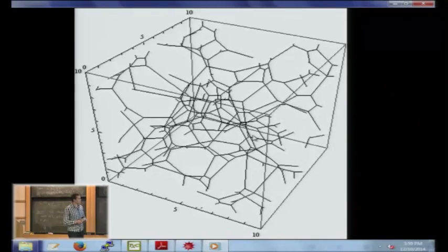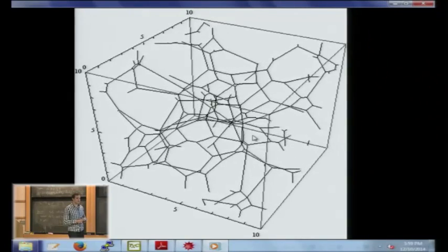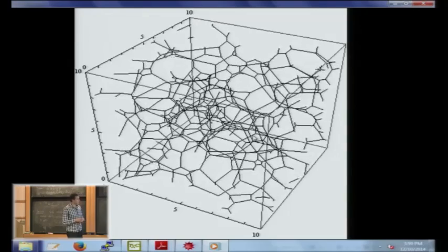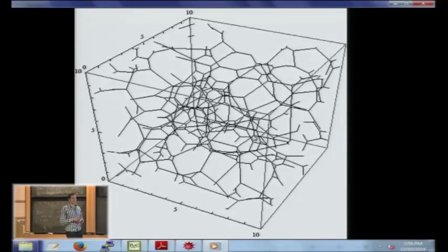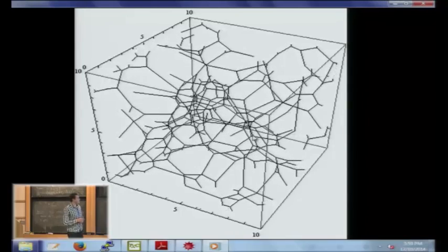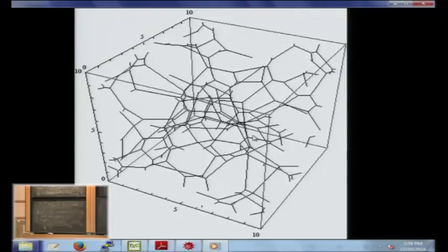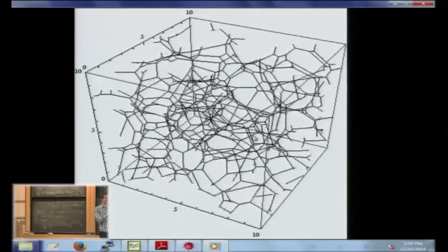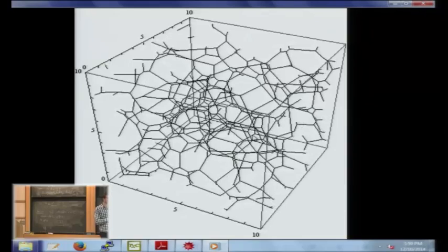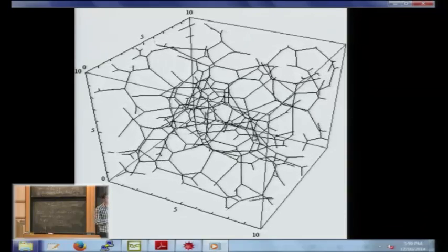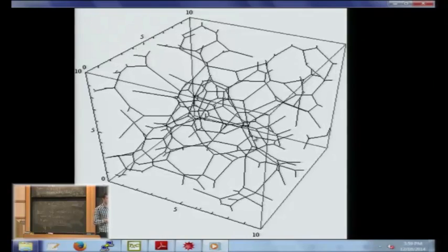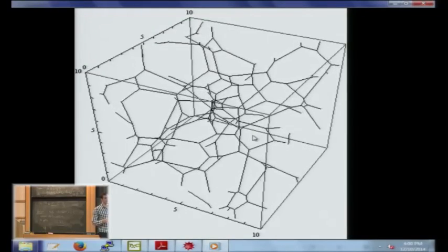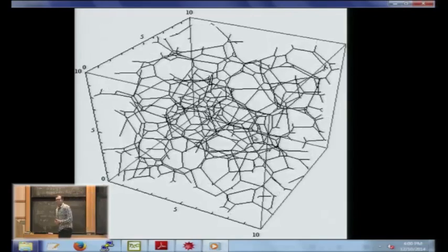Well, the energy, it's just we have a constant energy per unit length. There are several ways to compute this in practice. One way is you can just take the length of an edge and you assign the energy. These are discretized, so you have a polygonal curve, and at each point along the polygonal curve, you associate to it half of the neighboring segments. Or you can view it as an example of a curvature flow, and then you can use certain discrete notions of curvature. So there are several ways to implement this, and it turns out using the method of swatches, you can show that it doesn't really matter what you do. Same behavior.